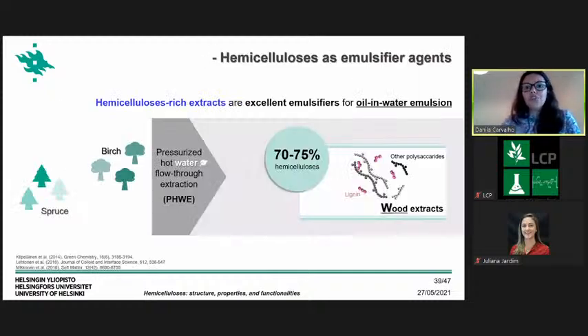But what was discovered by the group in which I am now, before I started this project, was that hemicelluloses are excellent emulsifier agents. They can really cover this oil droplet in a way that creates quite nice dispersion systems. And how they prepared the hemicellulose in this case for utilization as emulsifiers was using a hot water extraction. Simply, they used spruce and birch wood, subjected it to a hot water extraction, and then the water extract obtained, which contained more than 70% of hemicellulose, was tried and used as emulsifier.